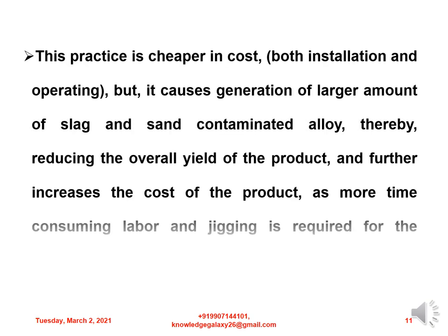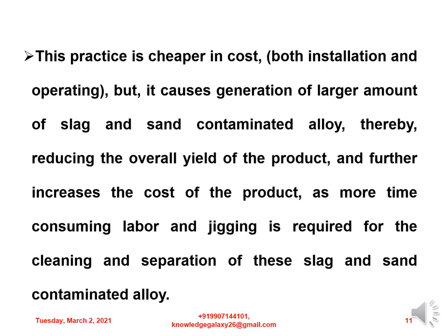This practice is cheaper in cost — both installation and operating — but it causes generation of a larger amount of slag and sand contaminated alloy, thereby reducing the overall yield of the product and further increasing the cost, as more time-consuming labor and jigging is required for the cleaning and separation of the slag and sand contaminated alloy.